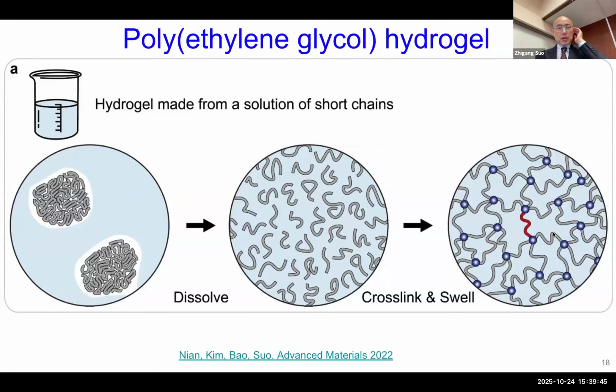Okay, so this is traditional making. People already know this: because you start with an existing polymer and do this crosslink, you need it to be stable in water, swelling with water. Then your chain cannot be very long. If your chain is very long, it can swell a lot of water. Then the material is just too floppy, you cannot use it.